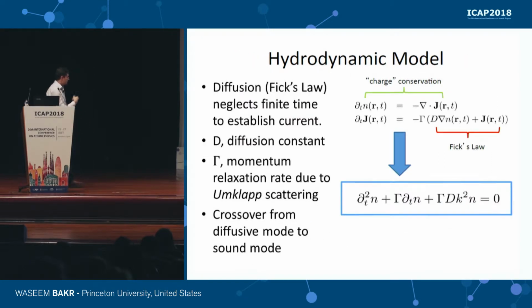OK, so here's our motivation for that. We have a simple hydrodynamic model that gives this form. So 2 equations. The first one is a simple charge conservation equation, which obviously has to hold. The second one is more of a phenomenological equation. So the idea here is that your first step might be to say, OK, the current is proportional to the gradient of the density through the diffusion constant. So that's Fick's law. Well, what that would give you is an amplitude that decays exponentially in time. So that correctly describes the long wavelength behavior.